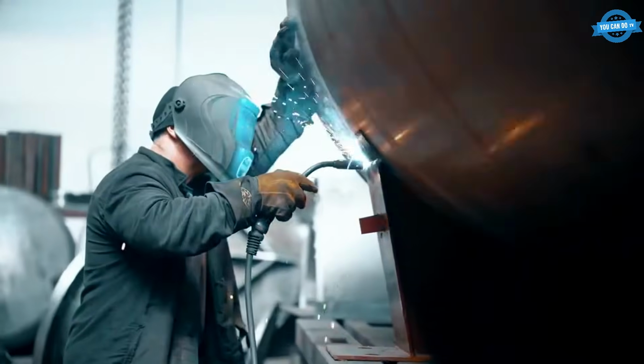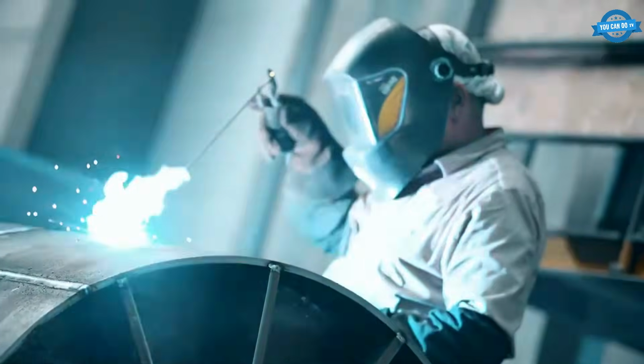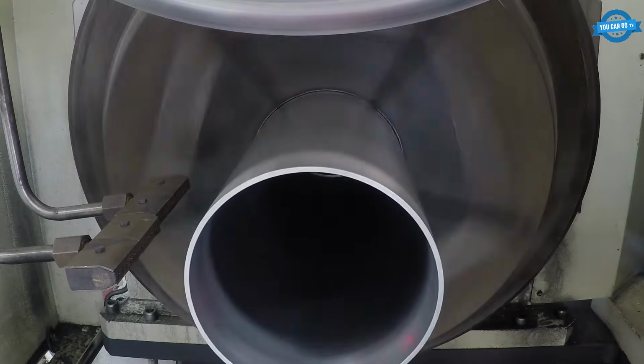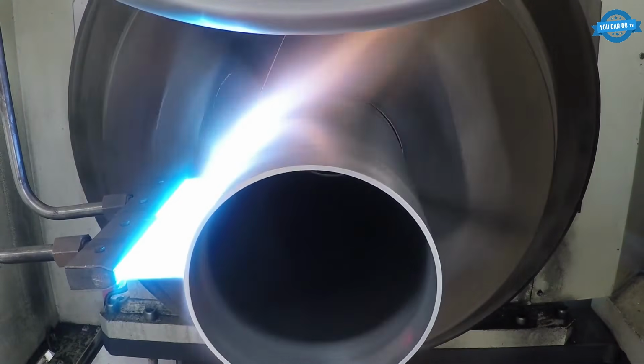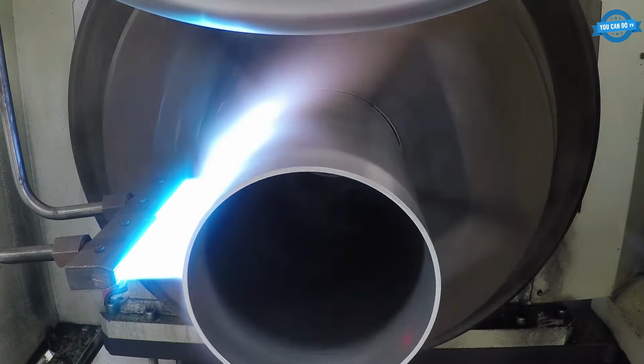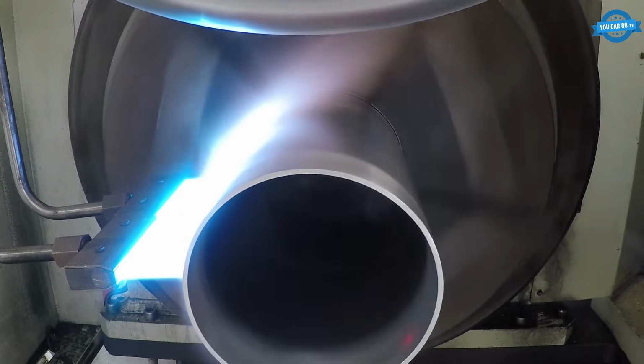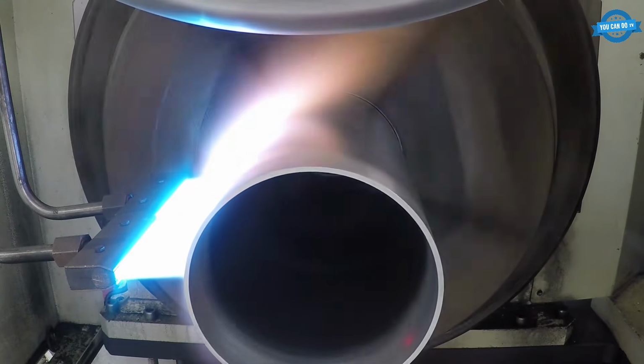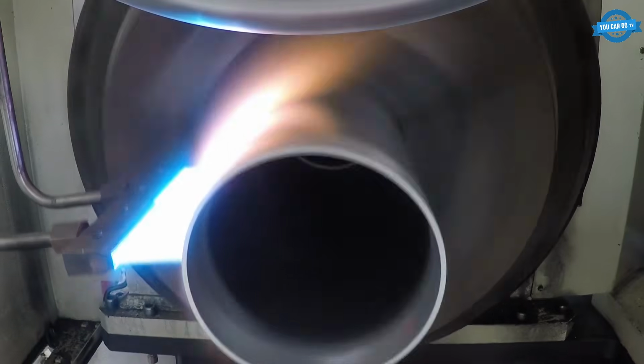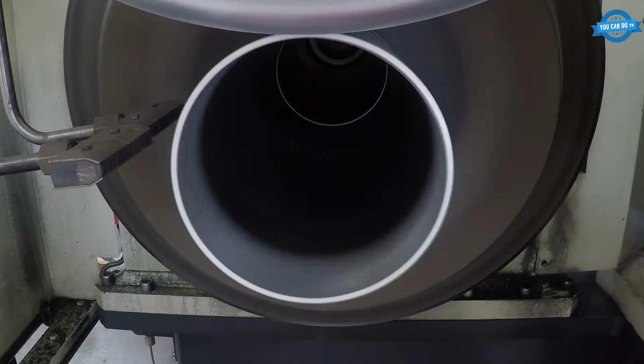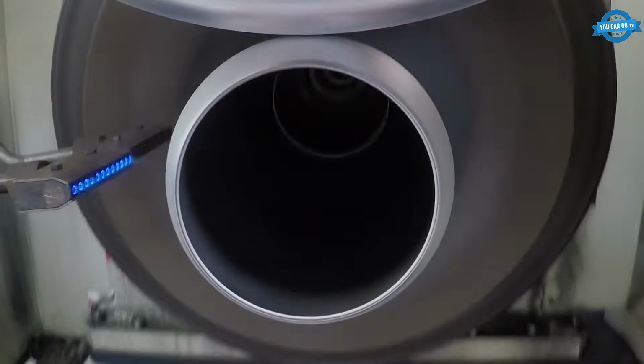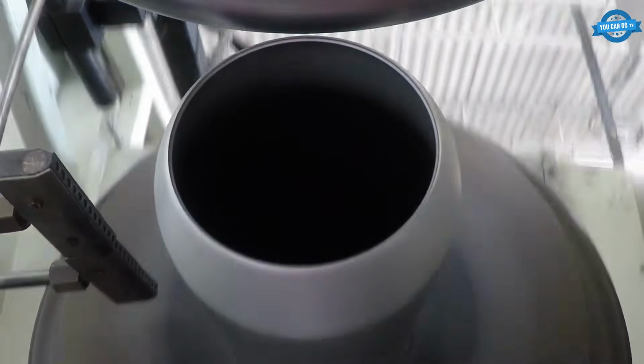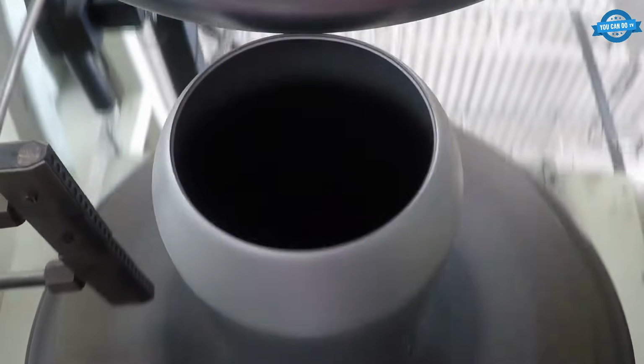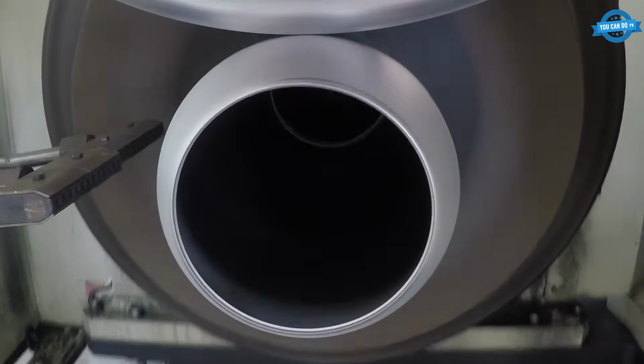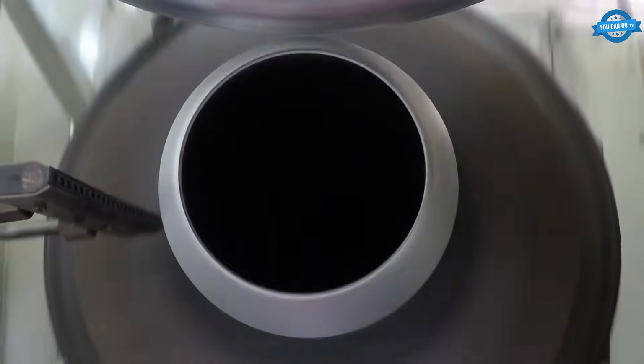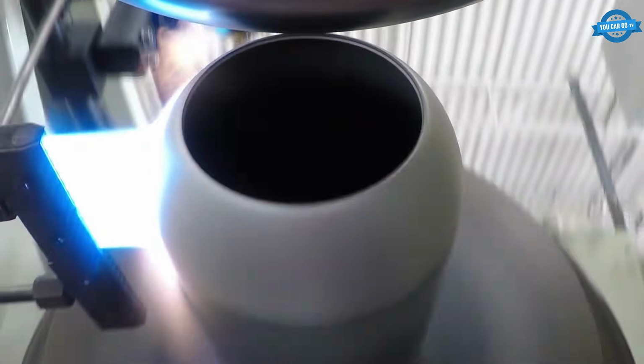But there's another way to make a curved metal shell that doesn't press anything at all. Instead of pressing a flat sheet down onto a die, spin it against a mandrel and let a roller do the work. A CNC metal spinning machine clamps a flat aluminum disc against a rotating mandrel. The mandrel shape is exactly the interior contour the finished part needs to have. The machine spins the disc at high revolutions per minute. A hardened roller then presses against the outside of the spinning disc and slowly moves along the mandrel profile. The metal flows plastically around the mandrel, thinning slightly and stretching to conform to the exact shape underneath.